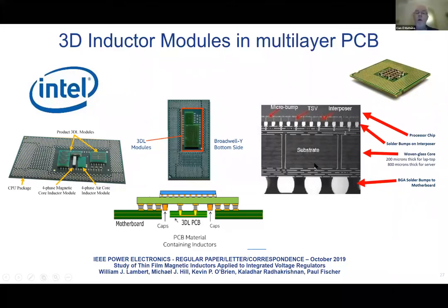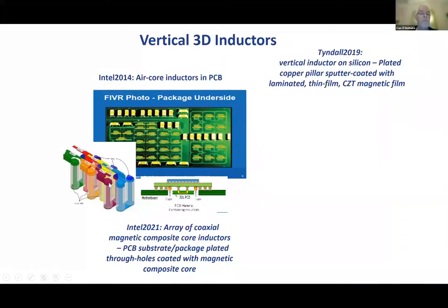But in this central area here, there's actually only organic material, which is part of the organic substrate. And what Intel have now looked at doing is, could you use this area in order to actually make your inductors disappear? And so they have moved from this idea of air core inductors to having these vertical copper pillars, let's say, in that central core area of the substrate, and they have wrapped magnetic material around that. So you get a vertical inductor. And that's a very interesting idea because now you're getting the maximum density of inductor that you would need for when more and more cores are used in those microprocessors.